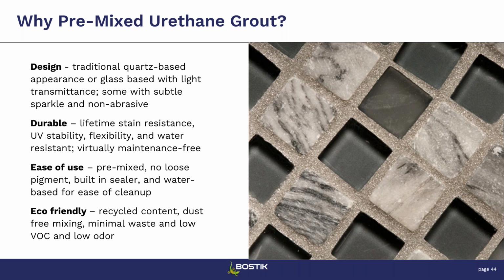With ease of use, it is pre-mixed, so you don't have to add the water to it and mix it up. So it's not as messy as a cementitious grout. It has that built-in sealer, so you will not have to seal it afterwards. And because it is water-based, it's easier for cleanup at the end of the job. It is also eco-friendly. With the glass bead portion of it, you do have that recycled content. So it is less dust or dust-free mixing because you are not mixing the water with the powder. It's also got minimal waste and low VOCs as well as low odor.